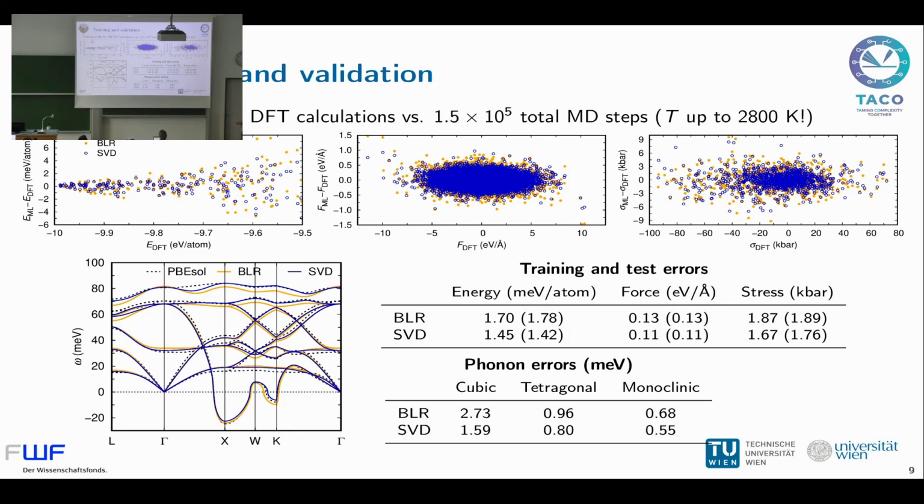This is the phonon band structure in the cubic phase. I wanted to show you this one in particular because you see it's got these negative or, well, imaginary phonon modes here that tell us that this structure is unstable, of course, as we know, at 0 temperature. But also, it's very, very important that our force field can quantitatively describe these imaginary phonon modes, because otherwise we cannot hope to be quantitatively describing the phase transitions.